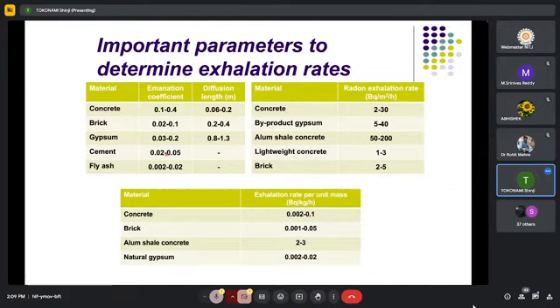Cement. The emanation coefficient is quite small compared to the other three, especially concrete. Cement 0.02 to 0.05. No data on diffusion length. Fly ash also much smaller than others.